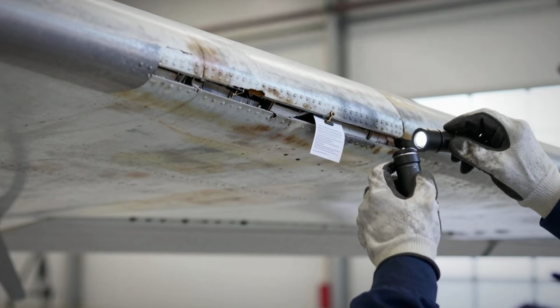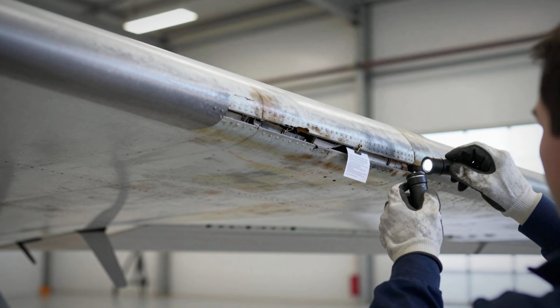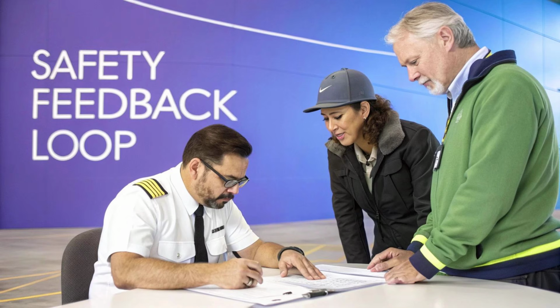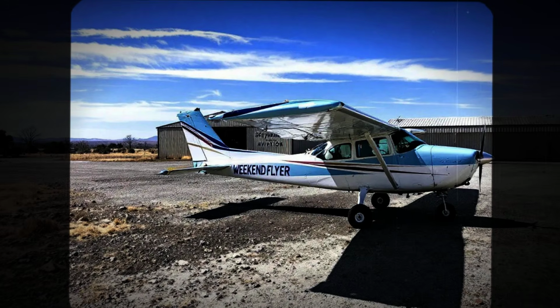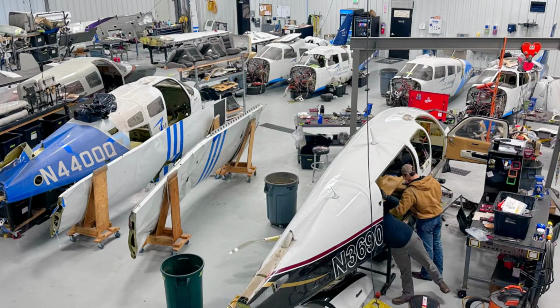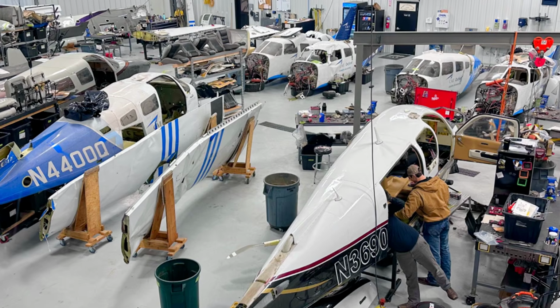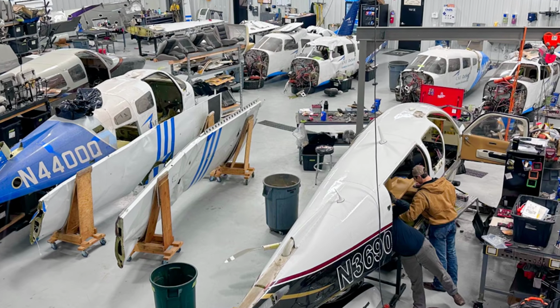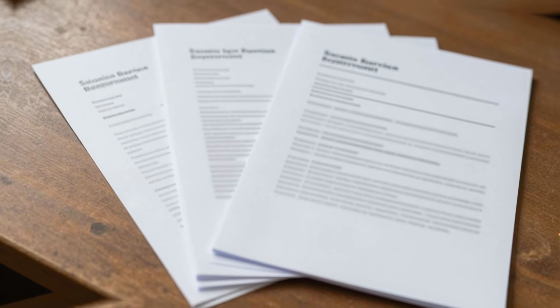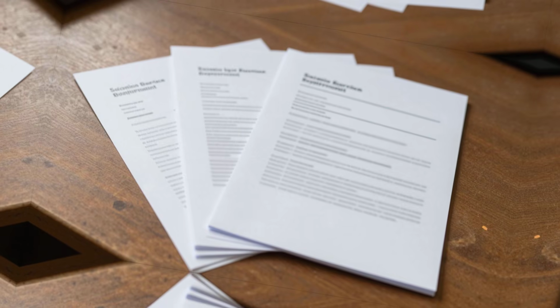Of 559 aircraft inspected before the rescission, 2 cracked spars were found, both in severe use aircraft. The FAA documented finding was that the safety benefit did not justify the risk caused by the inspection. Piper issued a voluntary service bulletin in 1988. It was not an airworthiness directive, and it was not required.